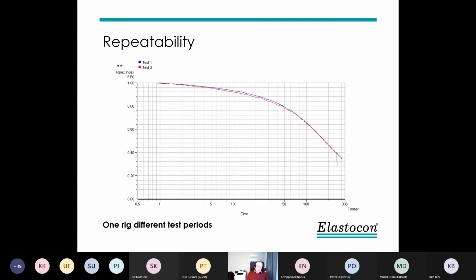In the end, you see the red curve goes down, and that's because we let it cool down to room temperature, and then the force will go down due to the shrinkage of the rubber. So the rubber shrinks about 10 to 20 times more than steel, or expands, whichever way you want to go.